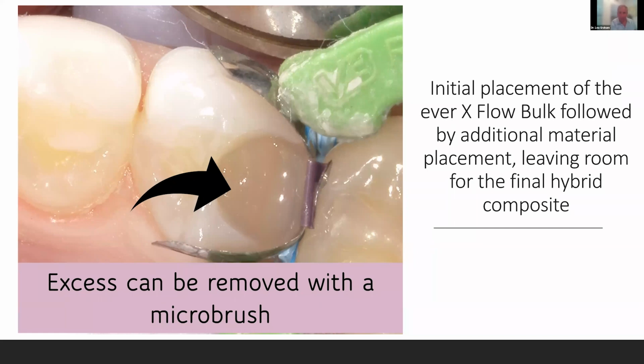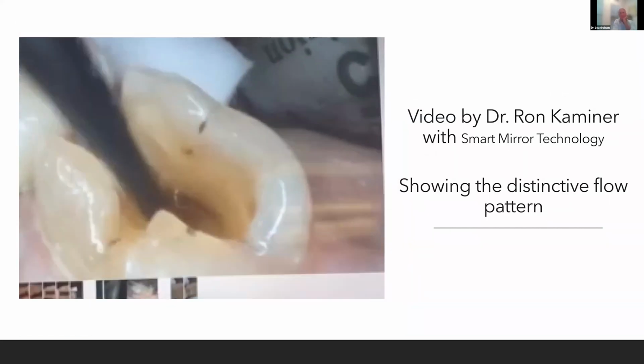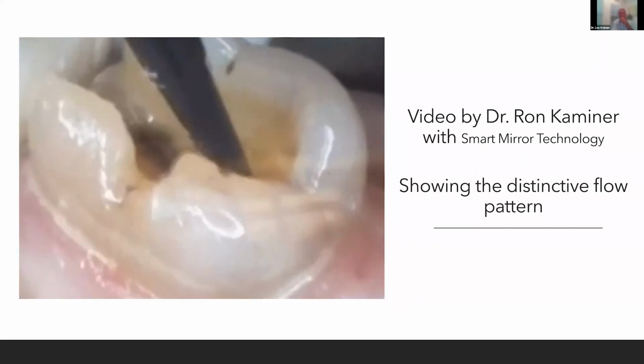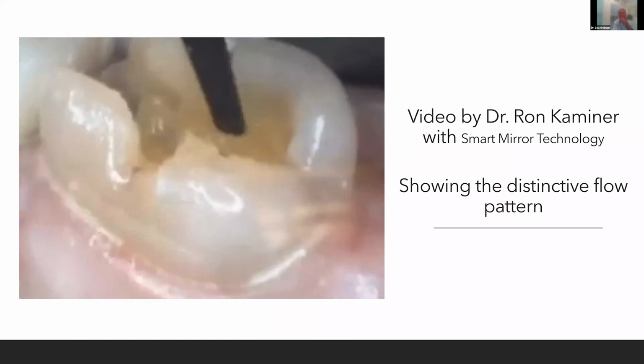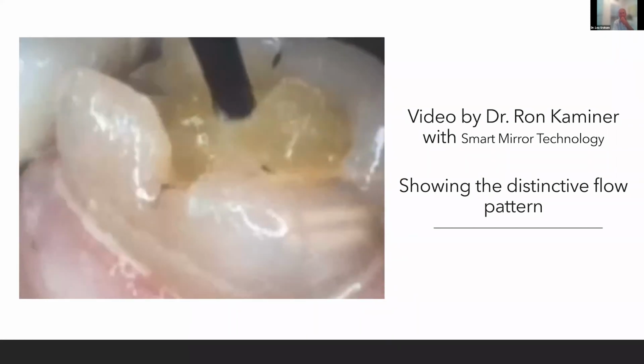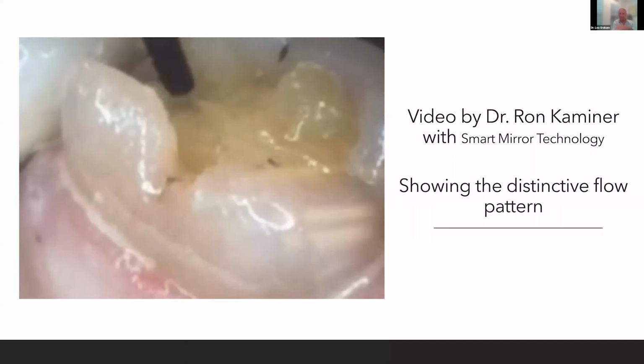Now I'm injecting literally a fiber reinforced flowable composite to minimize fracture. Forget a post. You don't need it. After about 10 seconds, you can pack it in and remove any excess with a micro brush. So I'm building this in the center and over the proximal over the SDR. This is from my buddy Ron. And you'll just see when you're injecting it, it looks a little bit like Vaseline. Let it self-level for about 10 seconds and then pack it.